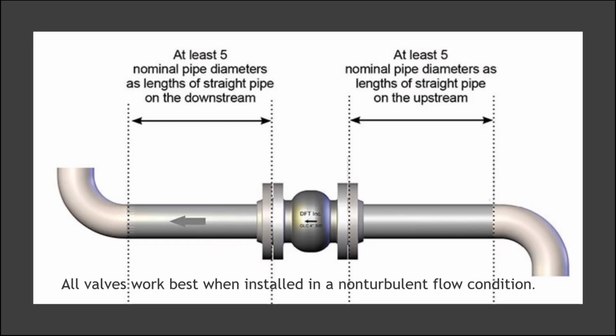All valves do work best when installed in a non-turbulent flow condition, so that means a minimum of 5 nominal pipe diameters both upstream and downstream of the valve to reduce the chances of turbulent flow through that particular valve.